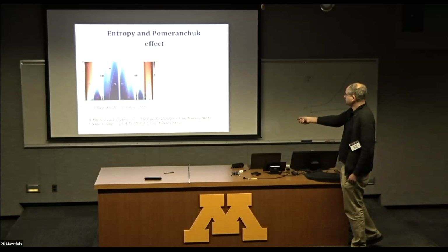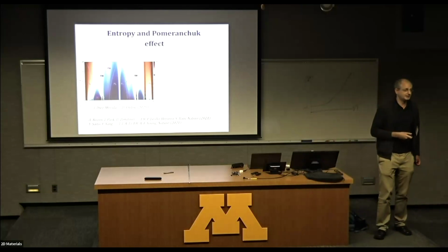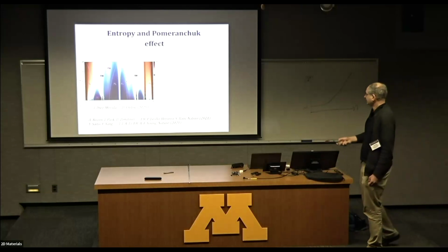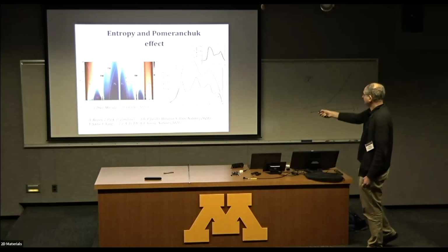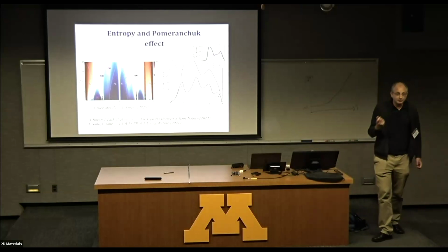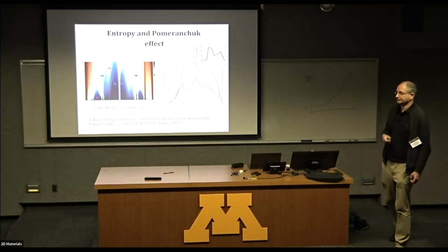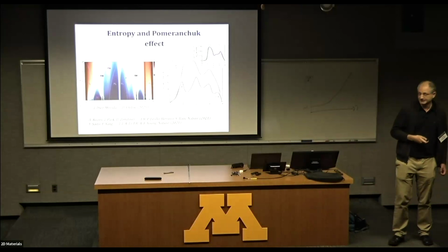Some resistive features shift in an interesting way as a function of temperature, suggesting that the more correlated state has a higher entropy. And this was later confirmed both by Shahal Ilani's group and by Andrea Young's group, using thermodynamic relations, inferring the entropy from temperature-dependent compressibility measurements.